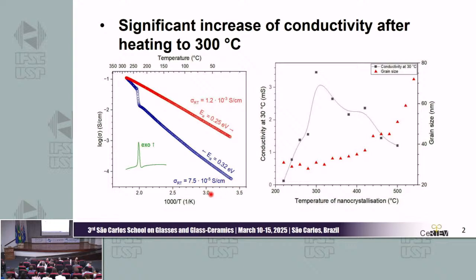When we take glass and heat it up, everything goes exactly as theory shows, but around the temperature of crystallization, conductivity rapidly increases. And what is also interesting is that the conductivity of materials which combine glass and ceramics is strongly related to this maximal temperature of crystallization.